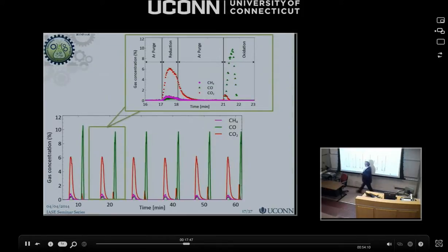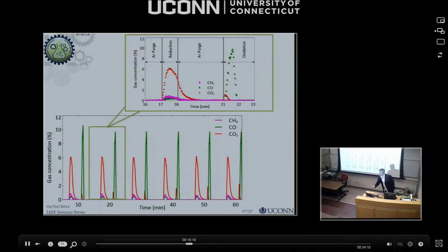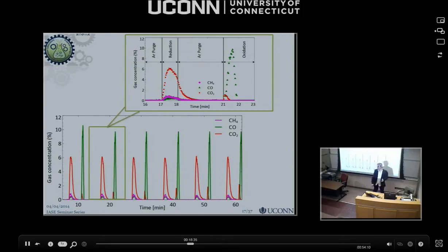A typical experiment shows the oxidation step and the reduction step. You get a lot of CO2 at some point during the reduction step, and we actually over-reduce it every time. During the oxidation step, we also get CO. We keep doing that — reduction, oxidation, reduction, oxidation — with a few steps of argon purging in between. If you focus on just one step, you have a peak of CO2 that drops down. This is not how one should run chemical looping commercially. In our case, the carbon formation reactions, especially with nickel, are very significant. We want to study and understand this well within the chemical looping environment.